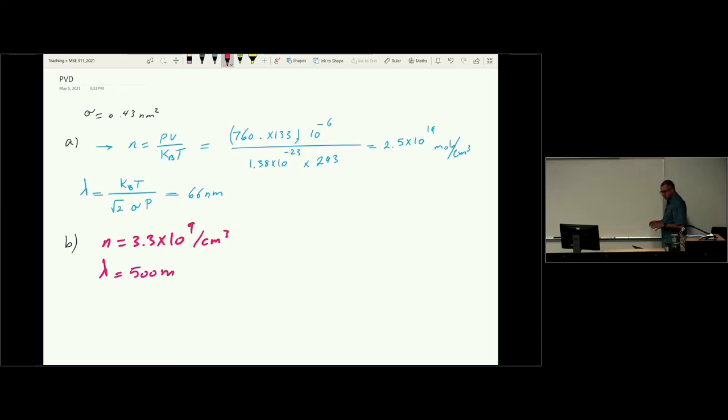So in the first case, first of all, you can see that we have far fewer molecules inside that chamber. If your chamber's typical dimension is, let's say, about half a meter to a meter in diameter and about 1 or 1.5 meters tall, you all of a sudden will have 10 to the 10 times less atoms in that chamber. So that's okay. It's probably not that easy to appreciate, but it's a lot less. We can appreciate it better when you look at the mean free path issue, right?